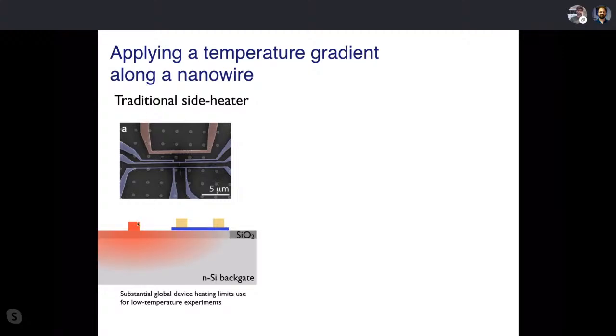And this sets up a heat gradient that looks something like this. You deposit a lot of heat into the substrate. Some of that spreads out to the side, and the nanowire sits on some amount of heat gradient then. This works great for experiments from room temperature down to 40 Kelvin or so. But then you cannot really get much below, because the only way to get a heat gradient is to really heat everything. So you cannot really work at near 0 Kelvin and have a heat gradient with the system. You have to choose one or the other.